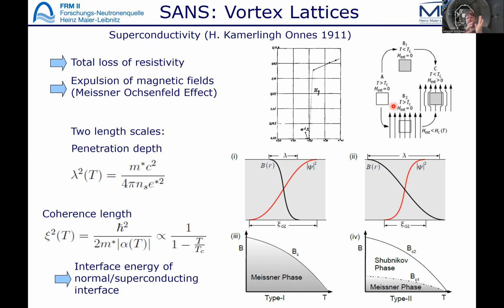So if you have an interface from normal conductivity to superconductivity, of course, it costs the superconductor energy to expel the magnetic field. On the other hand, the superconductor gains energy if it can condense electrons to Cooper pairs. And by looking at this interface energy, we can split the superconductors into two parts. One is called type 1 superconductivity, where the magnetic field is expelled until we reach a critical field. And the second, the larger family of superconductors, and the more interesting family, is the type 2 superconductors.